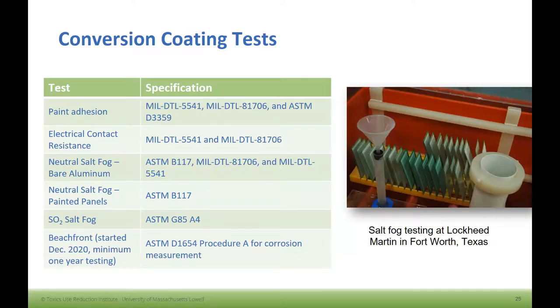So for the testing, we did a number of tests for the conversion coating. We did paint adhesion to make sure that the paint would stay on the surface. We did electrical contact resistance testing. We did neutral salt fog on bare aluminum. Then we did neutral salt fog on painted panels. Then we did SO2 salt fog. And we also did beachfront ambient long-term testing down at Kennedy Space Center at NASA again.